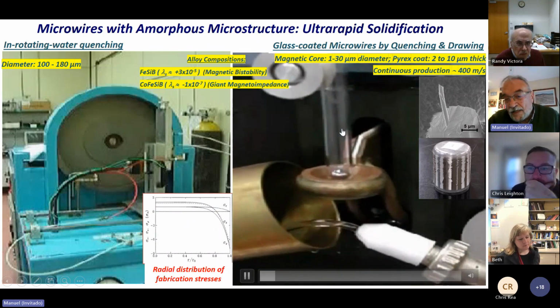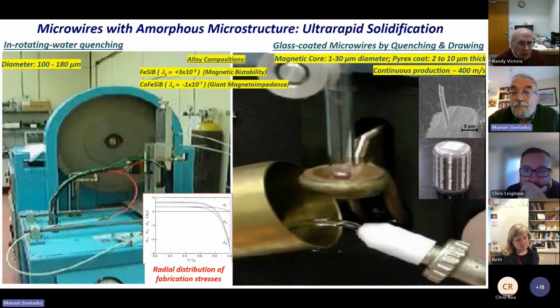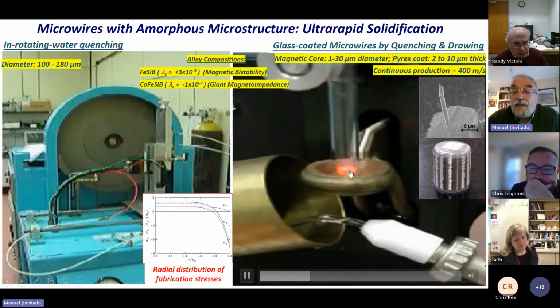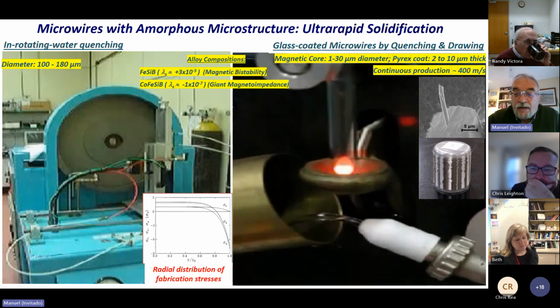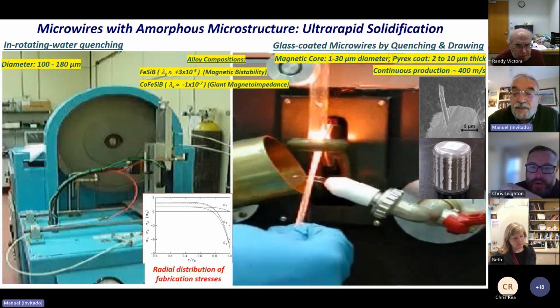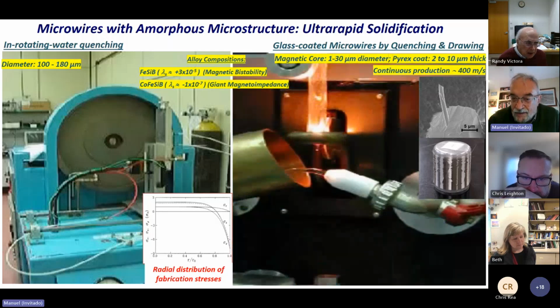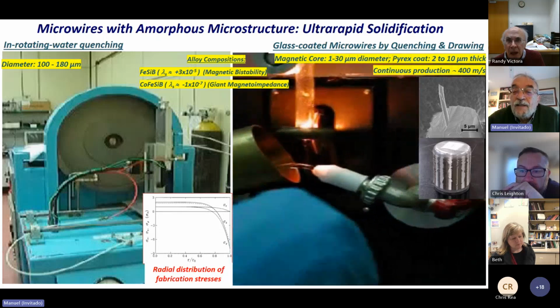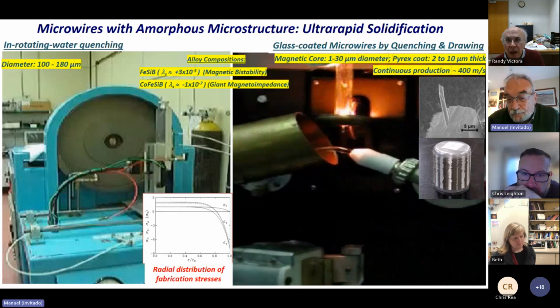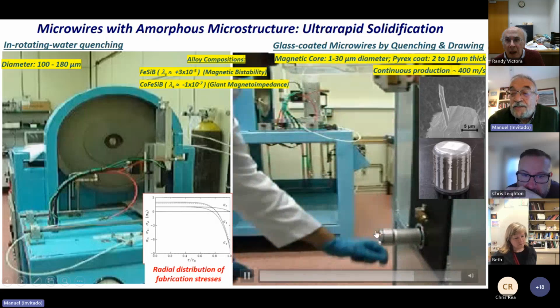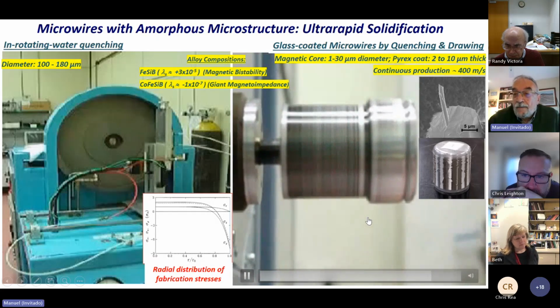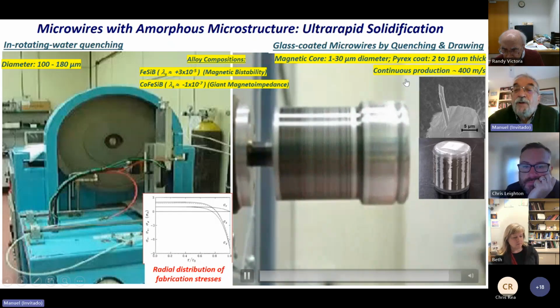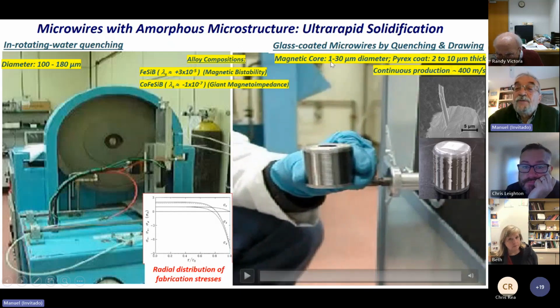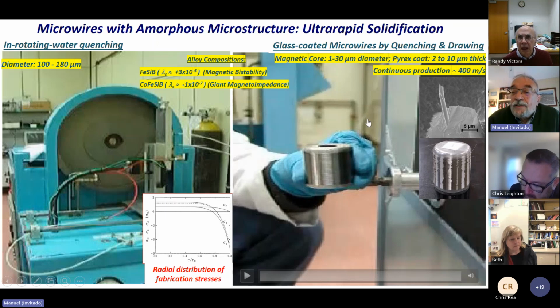So you see that with a mechanical machine, we get down the Pyrex with the polycrystalline pellet. So it gets heated up to 1200 degrees centigrade, roughly. And then we need a very skilled person who manually picks up the molten but very viscous metallic material coated by Pyrex. And then he collects everything in a rotating cylinder here. So it is possible to obtain the microwire with a production velocity of around 400 meters per second, and a diameter, as I mentioned, of 1 to 30 microns, coated by Pyrex that can be tailored to 2 to 10 microns thick, approximately. So, you see here a picture of the metallic core coated by the Pyrex.